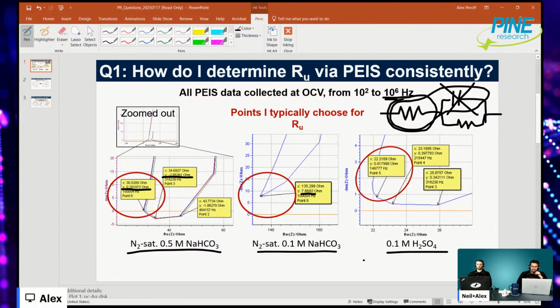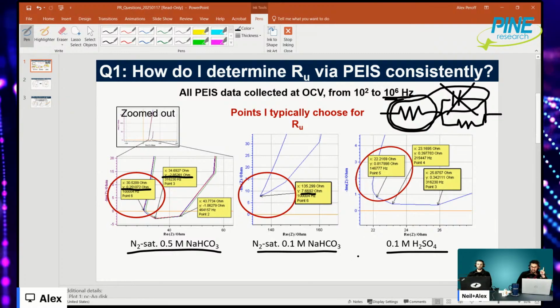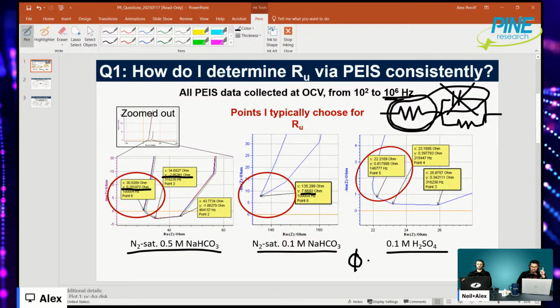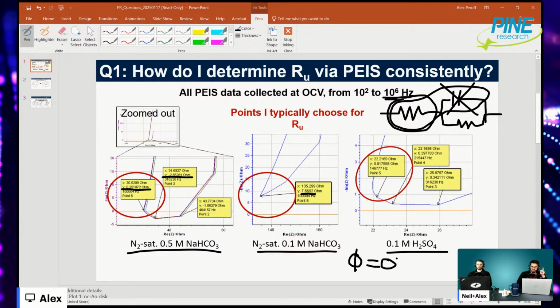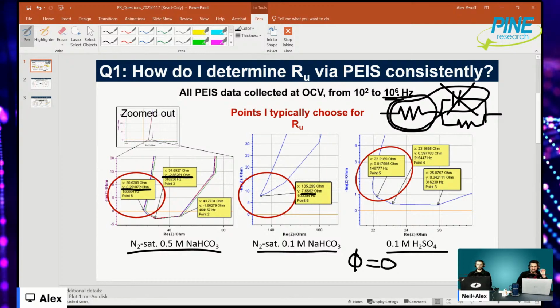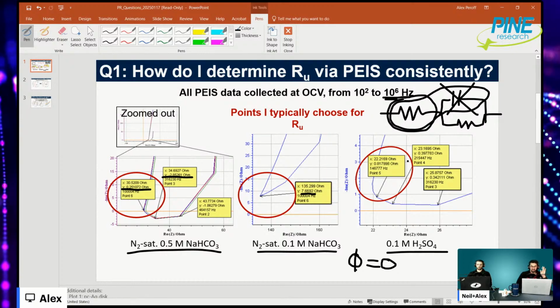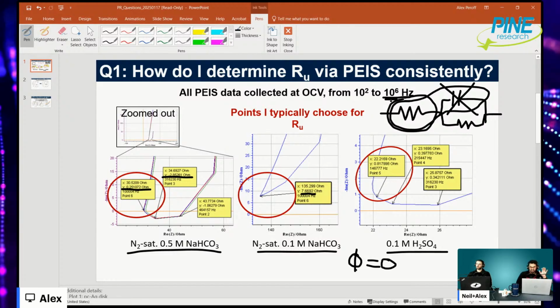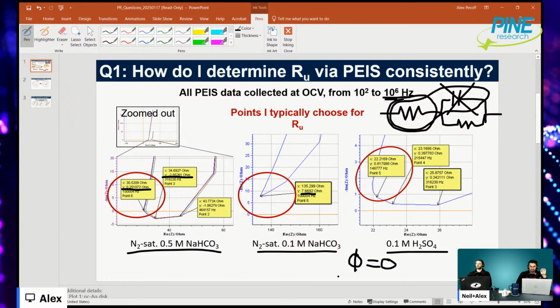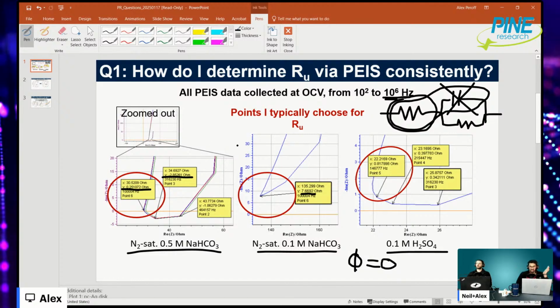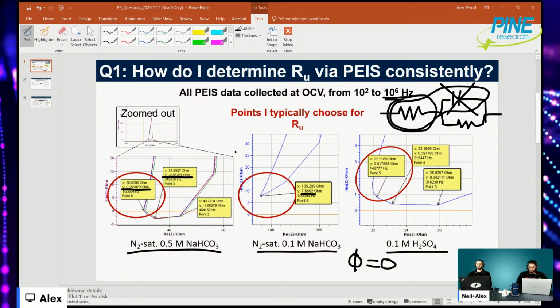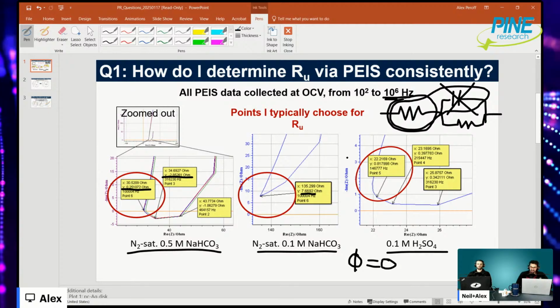You want to pick something where if you were to look at the Bode plot, the phase angle was closest to 0. And that's not always at 10 to the 6 hertz. It may actually be lower. It could be 10 to the 4 hertz or 10 to the 5 hertz where you actually see a phase angle that's closest to 0, and that would be your actual RU in your system.